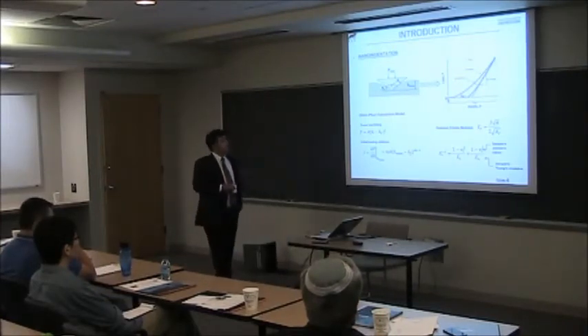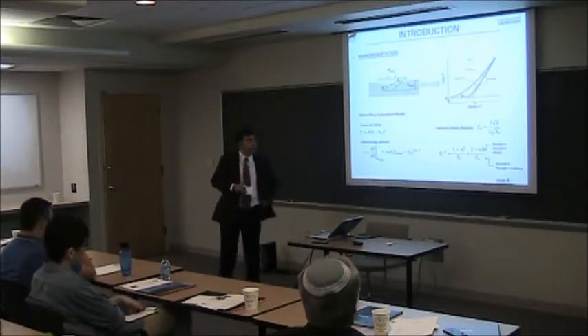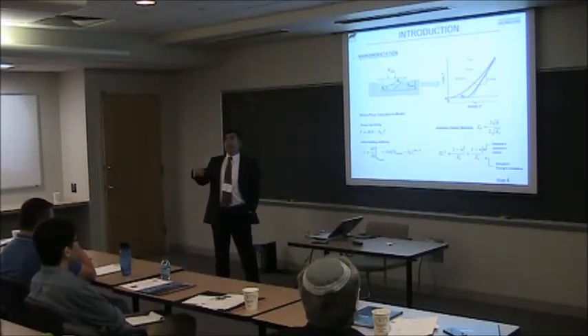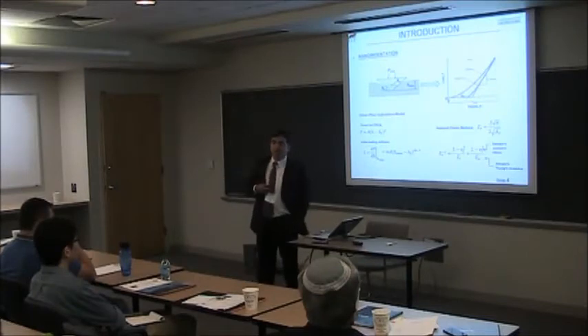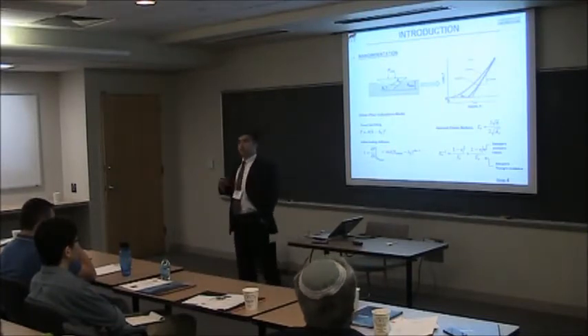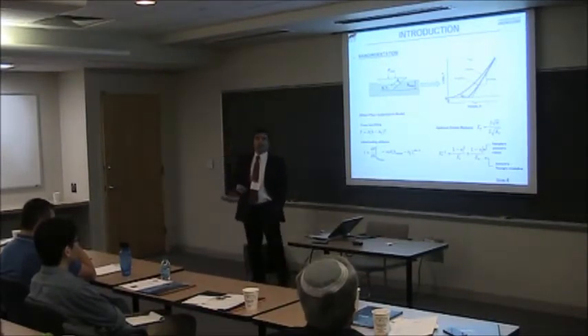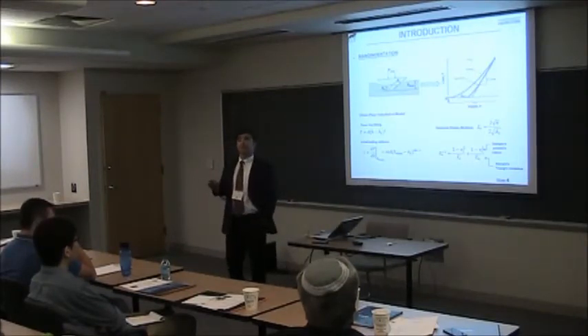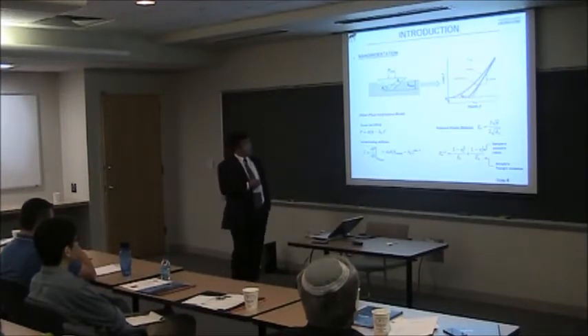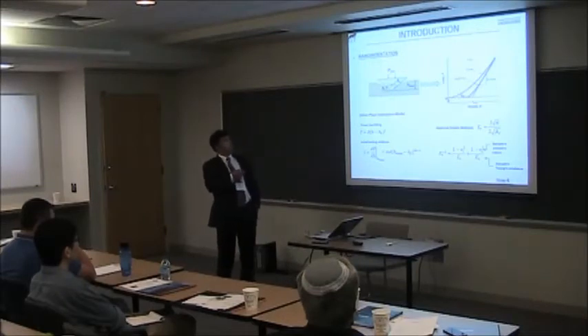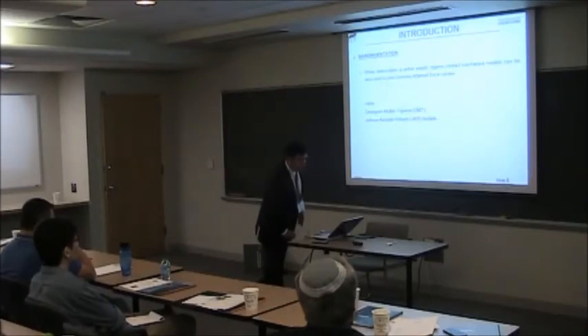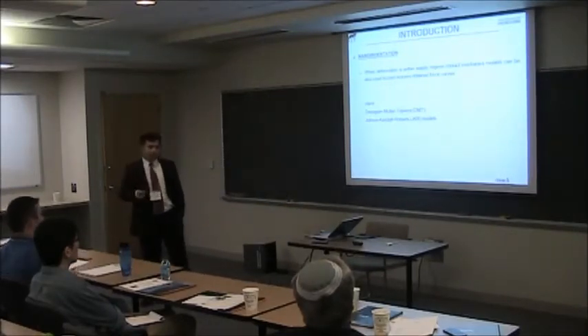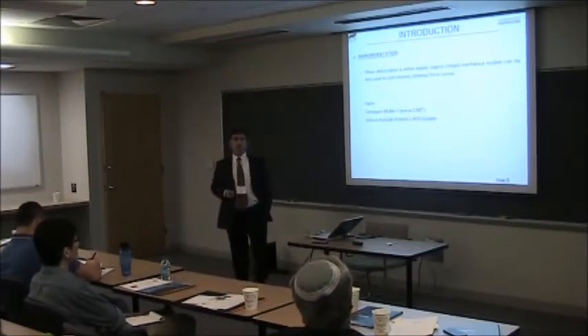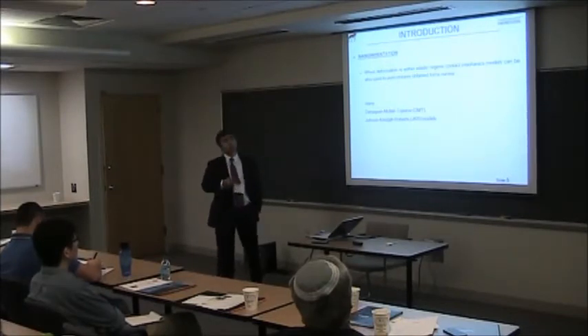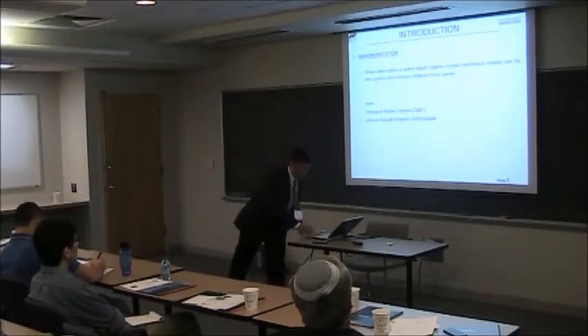And then in Kit's case, he used PDMS as a standard component to measure the Young's modulus with different methods. In our case, PDMS is our only target, but we don't want to tune our system on PDMS only. We want to have other materials which have known Young's moduli, so that the force calculations we get from the machine are more reasonable, more correct, or dependable. Then we can actually apply that system on the PDMS. Thus, we actually did silicon and then diamond probe indenting on top of silicon, creating some indentation and calculating that. So that's hard materials. Generally, Oliver Pharr you can use for hard and soft, but mostly if you have a plastic deformation, it's actually good. And if you have no plastic deformation, you're in the elastic regime. There are known methods, as again Kit mentioned in the morning.